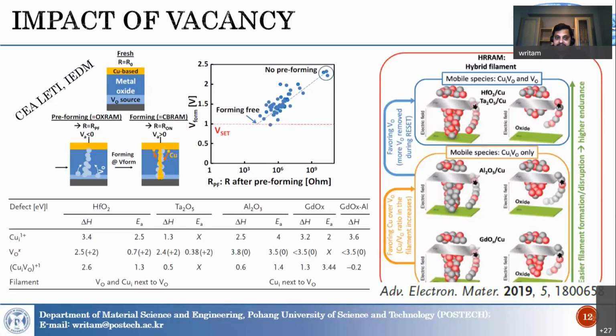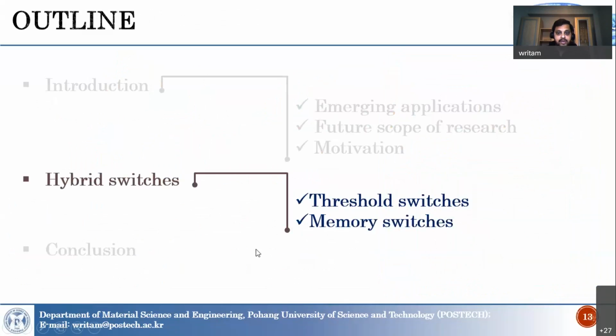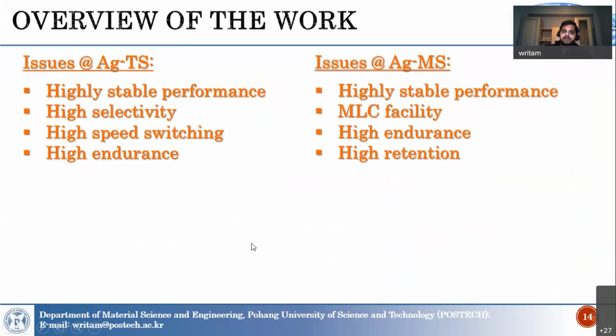Another study shows that with different kinds of vacancies, depending on the different switching material, the performance can change. So here in this work, we are mainly focusing on silver-based devices. The issue with silver-based threshold switching devices is highly stable performance, as I've discussed already, and then high selectivity, high speed switching, and high endurance.